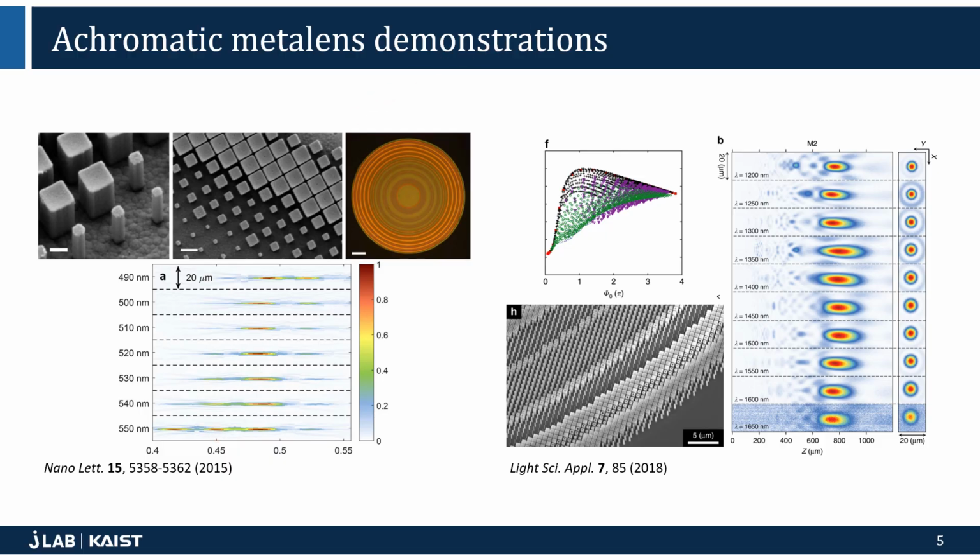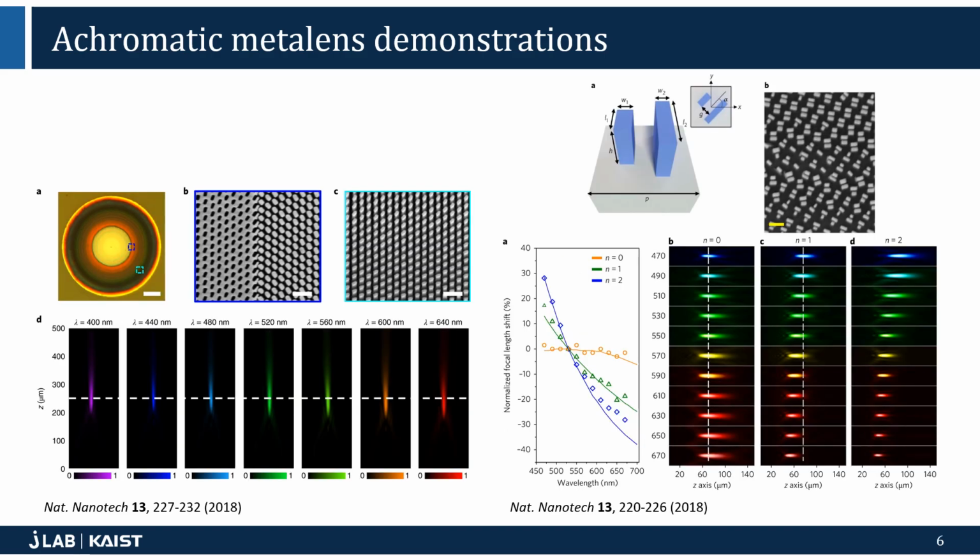This means that the efficiency of these devices is inherently limited. These parasitic focal spots can be removed by disentangling the phase from the dispersion, which we can also call group delay. This disentanglement has so far been achieved by using polarized light and the concept of geometric phase, and then rotating these structures.